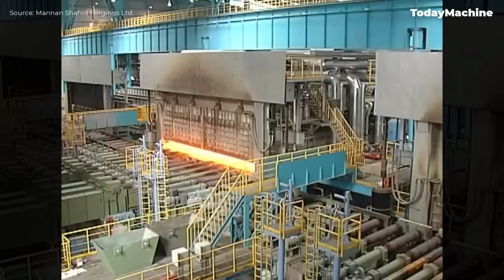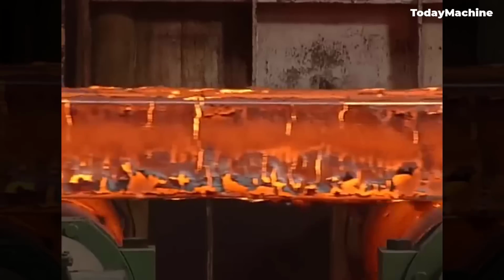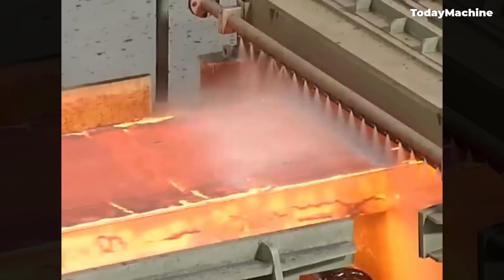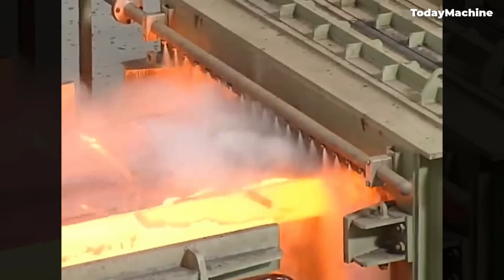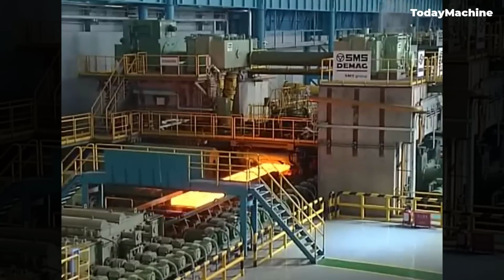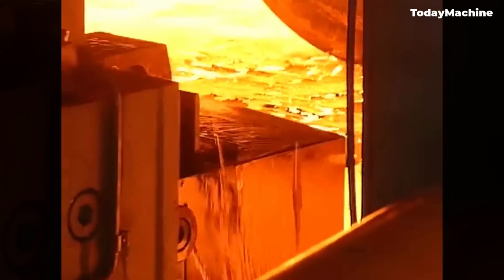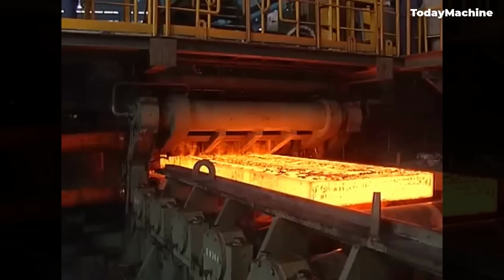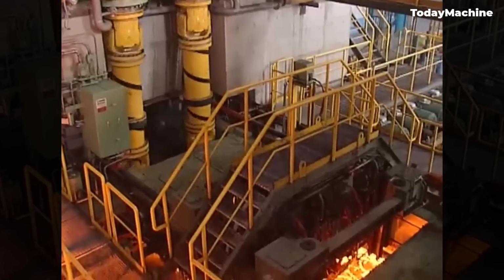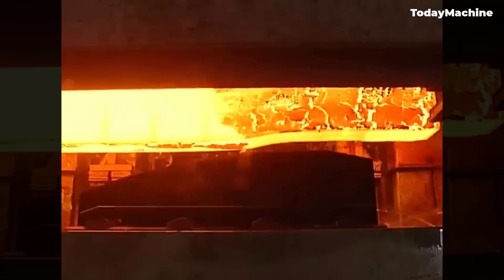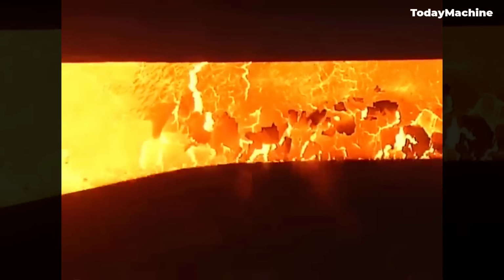The hot strip mill is designed with cutting-edge technology, boasting an annual production capacity of 4 million metric tons. It can produce a diverse range of products, including multi-phase steels and high-strength pipe grades up to X80. The mill's capabilities include processing slabs into strips with thicknesses ranging from 1.5 to 19 millimeters and widths between 750 to 2,130 millimeters.